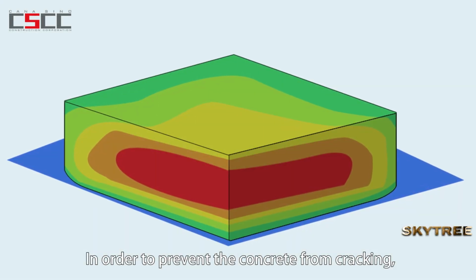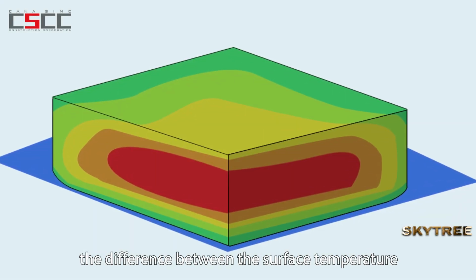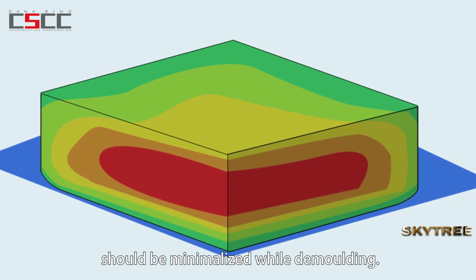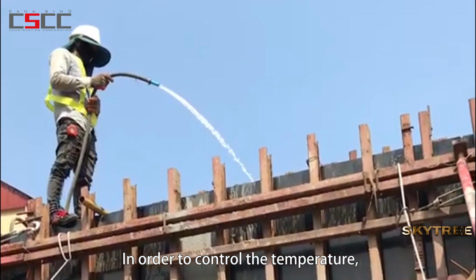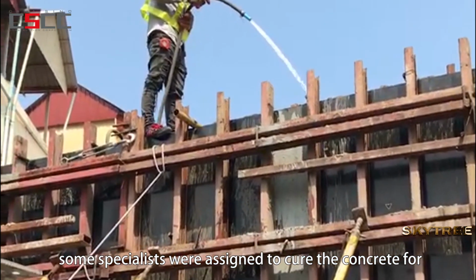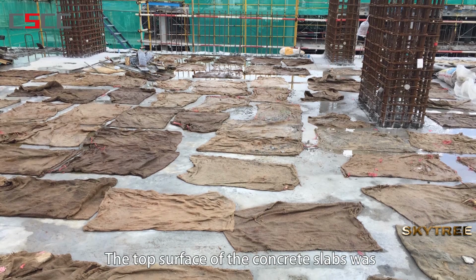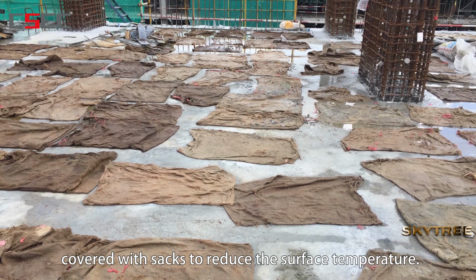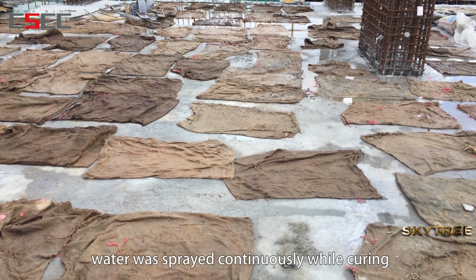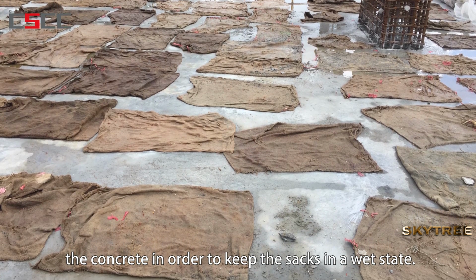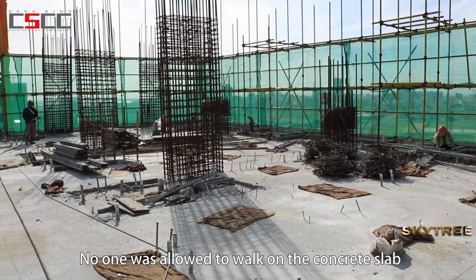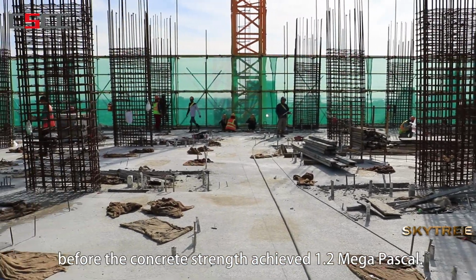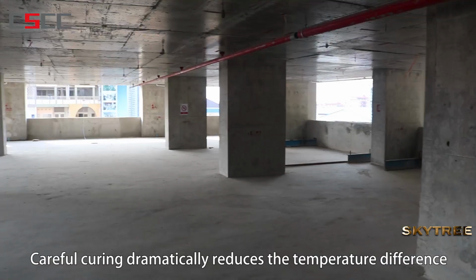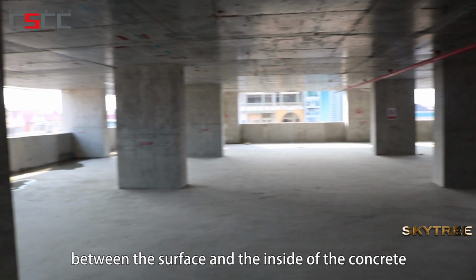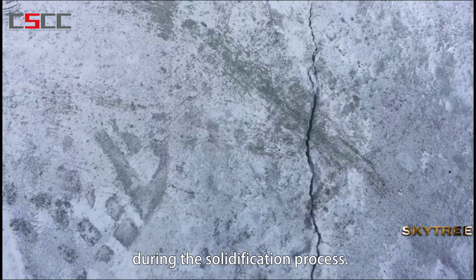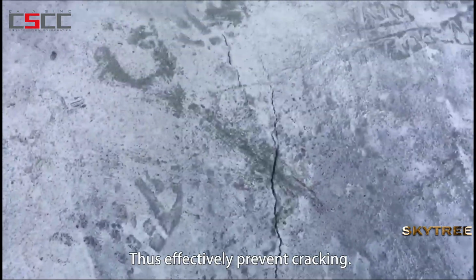In order to prevent the concrete from cracking, the difference between the surface temperature and the inside temperature of the concrete should be minimalized while demolding. In order to control the temperature, some specialists were assigned to cure the concrete for at least 7 days. The top surface of the concrete slabs was covered with sacks to reduce the surface temperature. Additionally, water was sprayed continuously while curing the concrete in order to keep the sacks in a wet state. No one was allowed to walk on the concrete slab before the concrete strength achieved 1.2 megapascal. Careful curing dramatically reduces the temperature difference between the surface and the inside of the concrete during the solidification process, thus effectively prevent cracking.